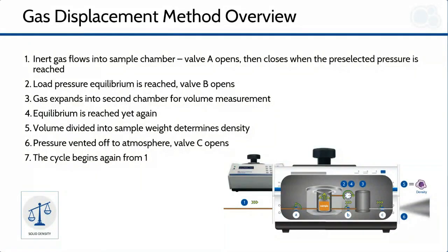The gas pycnometry technique uses gas displacement to measure accurately the skeletal volume of porous materials. Inert gases such as helium or nitrogen are used as the displacement medium. The material is placed in the sample chamber of known volume. The appropriate inert gas is admitted, pressure equilibrated, and then expanded into another calibrated internal reference volume. The pressures measured at equilibrium in the sample chamber and after expanding into the reference volume allow the computation of the sample solid phase volume. Helium molecules rapidly fill pores as small as 1 angstrom in diameter. Only the solid phase of the sample displaces the gas. Dividing the sample weight by this volume gives the material skeletal density.